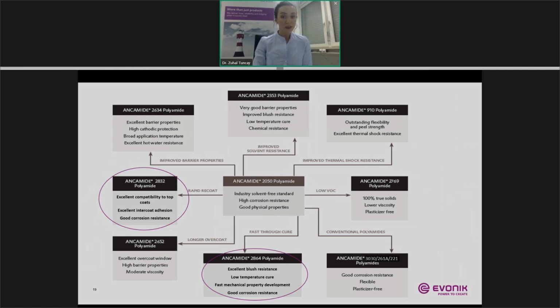2353 has excellent solvent resistance, where 2634 provides significantly higher corrosion protection, allowing the formulators to reduce expensive anti-corrosive pigments. Okay, we move to 2652. It provides longer overcoatability. This means that the coating can be overcoated without the issue of poor intercoat adhesion for up to 3 months after initial coating has been applied.